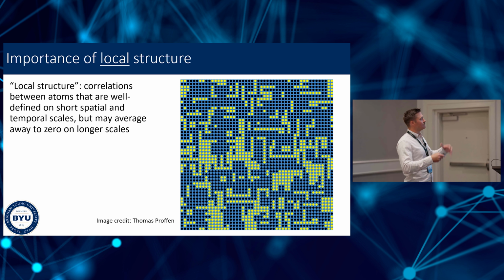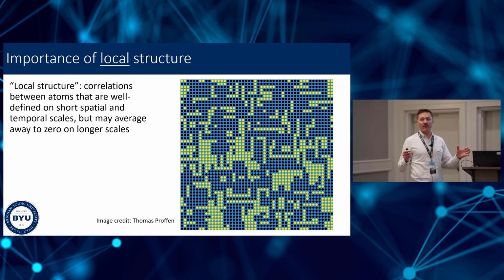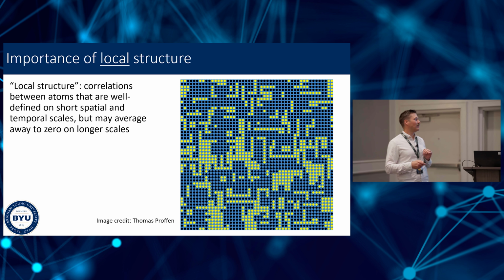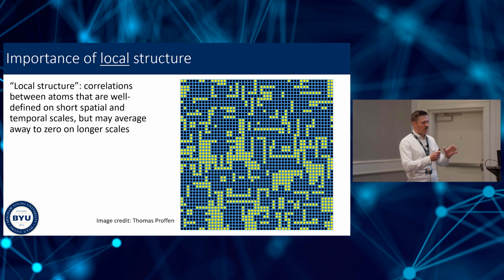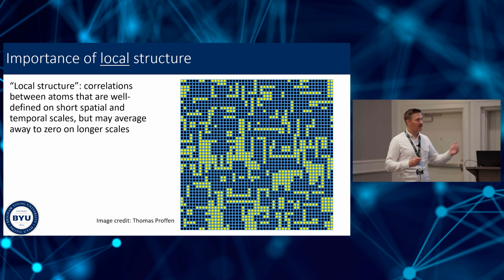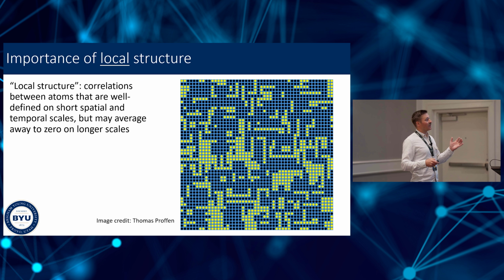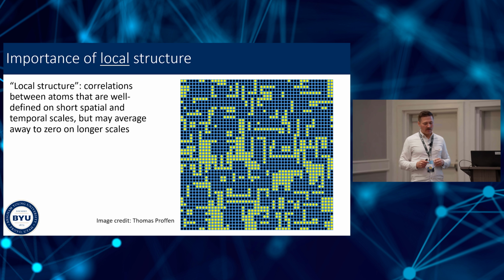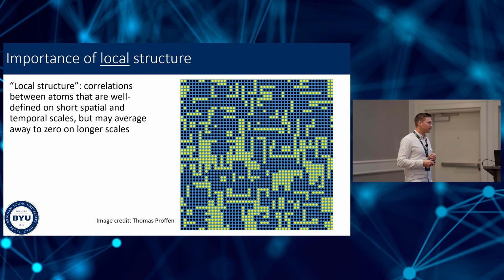It represents some binary alloy with half the atoms being yellow and half the atoms being black. On average, each atomic site has 50% yellow atom, 50% black atom. Okay, and there's no long-range ordered arrangement of these yellow and black atoms. Nevertheless, if you look locally, there is clearly a preference for like atoms to cluster together. All right, so this would be an example of local chemical short-range order in some binary compound.